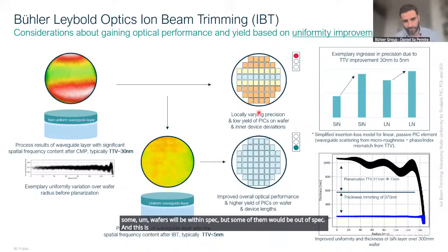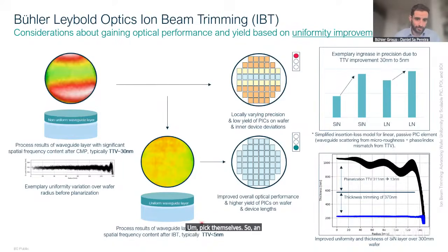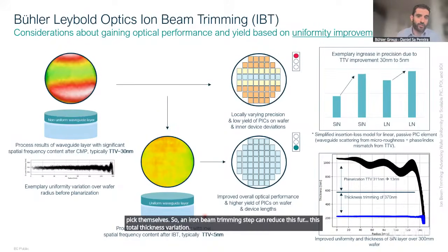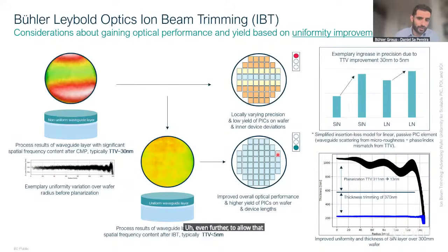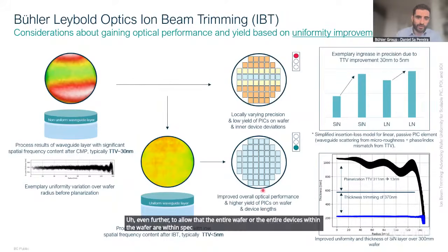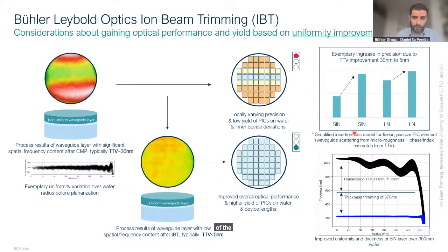And this is because the precision of the waveguides and the precision of the thickness is very important, and even more important for PICs themselves. So an ion beam trimming step can reduce this total thickness variation even further to allow that the entire wafer or the entire devices within the wafer are within spec. So basically the end result is that you have an improvement in the yield of the PIC performance of the PIC platform production.